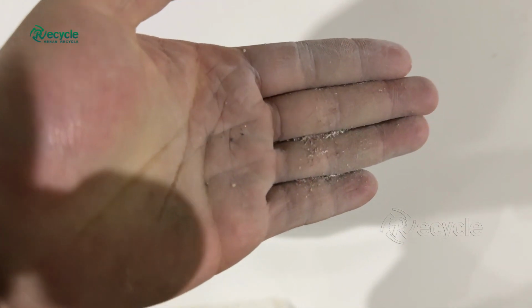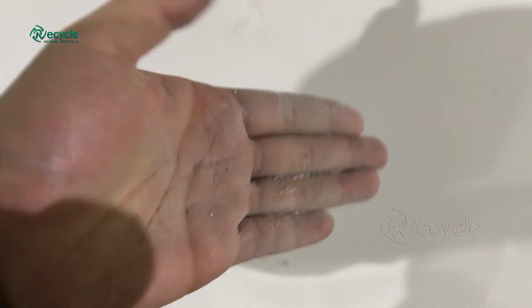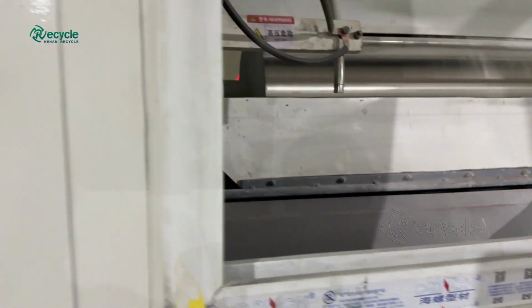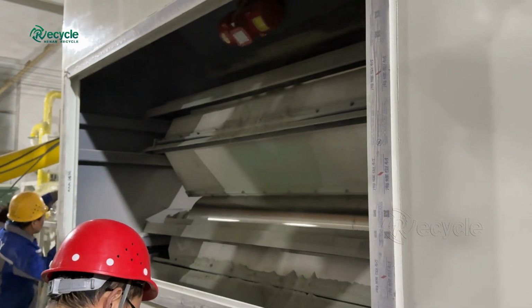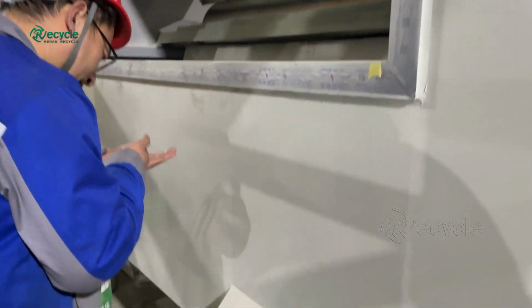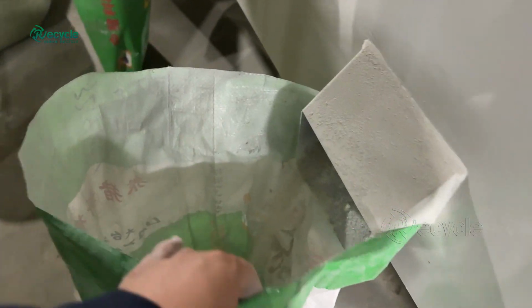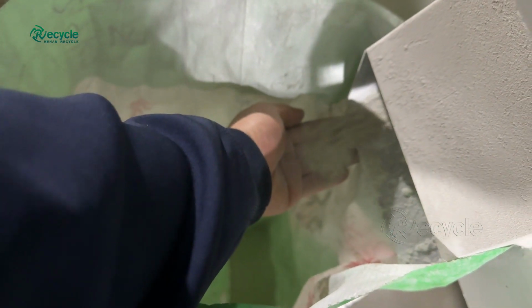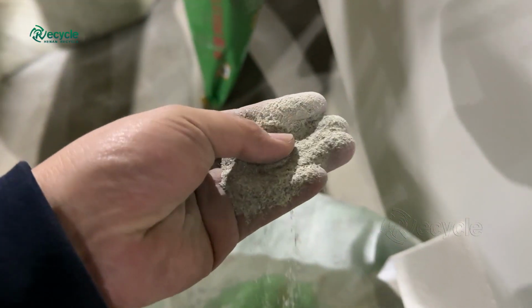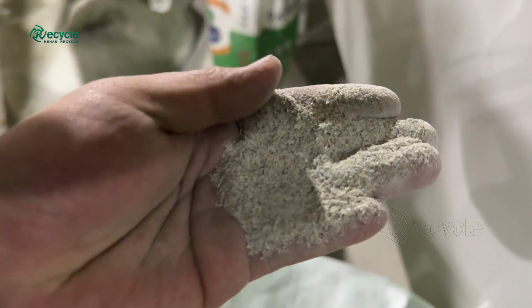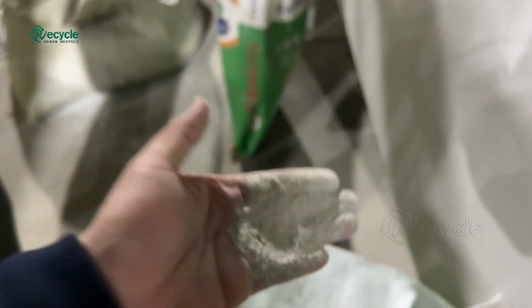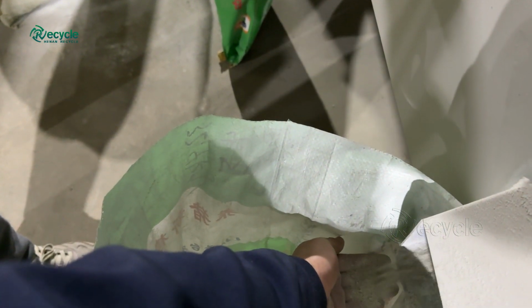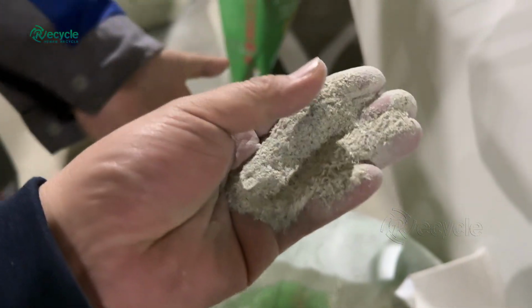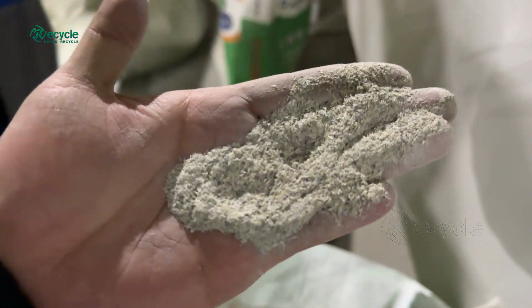The crushing and separation line operates at a processing capacity of 300 kilograms per hour and is engineered for continuous industrial operation. By combining controlled thermal dismantling with multi-stage mechanical crushing, closed-loop grinding and screening, and purely physical separation technologies, this PCB recycling solution delivers high recovery rates without the use of chemical reagents. It provides recycling companies with a reliable, environmentally compliant, and economically efficient way to convert waste circuit boards into valuable secondary raw materials.